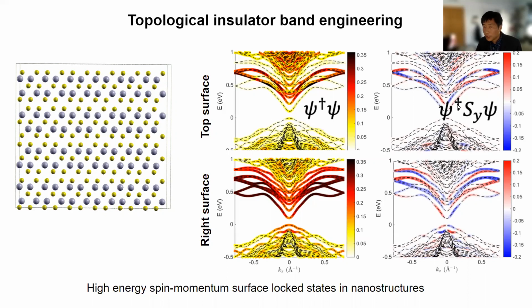So with that, since the spin momentum locking survives, we should also expect to see a Rashba Edelstein effect in this nanostructured material. That's the first important conclusion: even after going from a slab to a nanowire, quantum confinement still preserves that spin momentum locking, and therefore we should still expect a Rashba Edelstein effect.